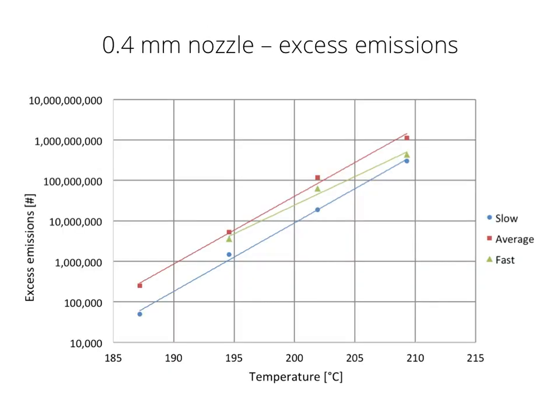As I already mentioned before, excess emissions, and I'm just quickly going to go over these, are the particles that you emit because of the heater block not having a homogeneous heat distribution at the beginning of the extrusion process. We can again explain those increases in particle emissions with an exponential function. Again, the y-axis is logarithmically plotted over the measured nozzle temperatures. This is the 0.4 millimeter nozzle, and we can explain this increase with an exponential function, but the fit is only okay-ish, I would say.